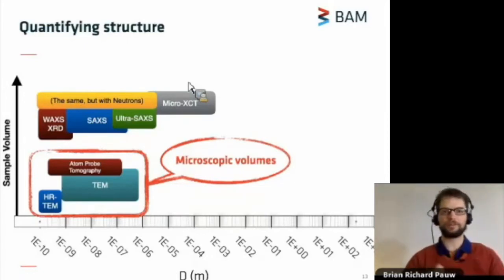The instruments are a lot bigger. They're usually situated around a special type of nuclear reactor, which is intended to create a lot of neutrons. The instruments are not 10 meters long, but they're hundreds of meters long. The shielding is usually thick blocks of concrete, and also the sample is an order of magnitude bigger. So, where with X-ray scattering techniques we're typically looking at samples on the order of a cubic millimeter, with neutrons you're looking at samples on the order of a cubic centimeter. So, that means you have a few orders of magnitude more in volume that you're analyzing there.